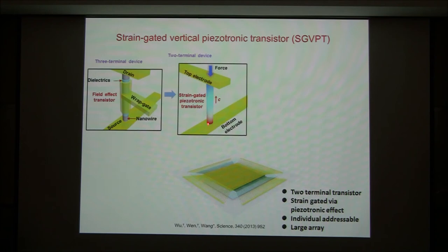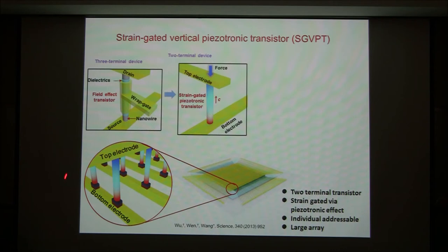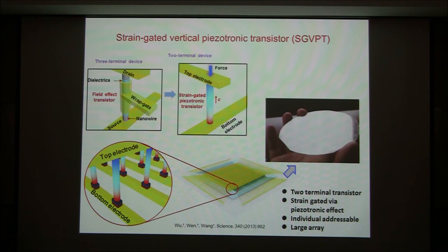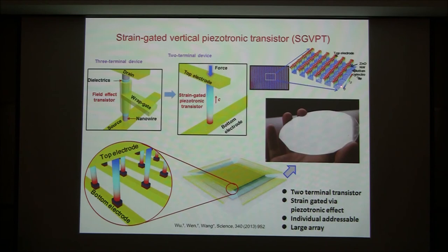If this is possible, you can build a crossbar electrode and have many devices built. Based on this, we have fabricated a chip — this is called the piezotronic transistor array chip. On a one-centimeter area, we have the devices inside with nanowires, electrodes, packaging materials, and filling materials. It totally takes 31 steps from nanowire material, sample preparation, nanowire growth, device fabrication, to packaging. This is a piezotronic chip.